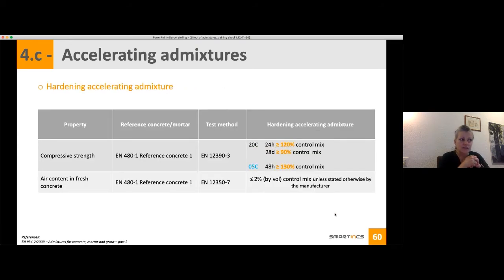In hardening accelerating admixture, here it will increase the hardening rate. The first requirement relates to the compressive strength: at 20 degrees at 24 hours, you should get more than 120% of your control mix. And at 28 days, you should have more than 90% of your control mix.